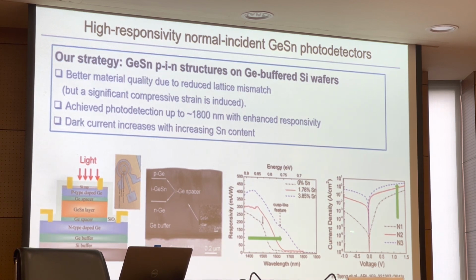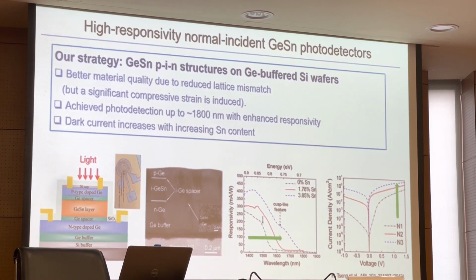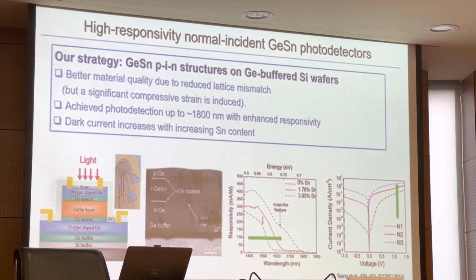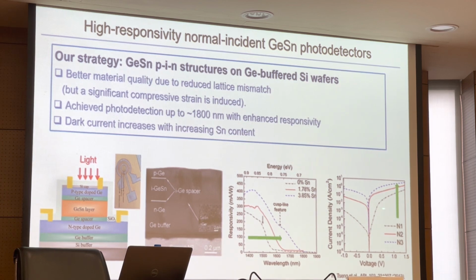But one problem for germanium tin photodetectors is dark current, because when we reduce the bandgap energy, the dark current also increases. For germanium tin photodetectors, as you can see here, when we increase the tin content, the dark current also increases significantly.